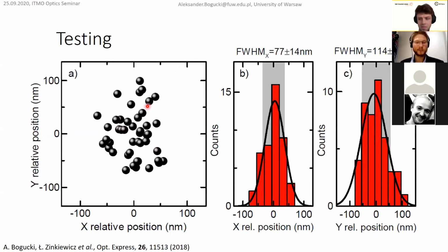And these are results of 46 consecutive put-ons and put-outs. So we made that 46 times without stopping. Each, let's say, introduction of the optical fiber took about 3 minutes. So it takes 3 minutes to fully dock in and then dock out. And as you can see, this precision is pretty good. The FWHM is well below 120 nanometers.